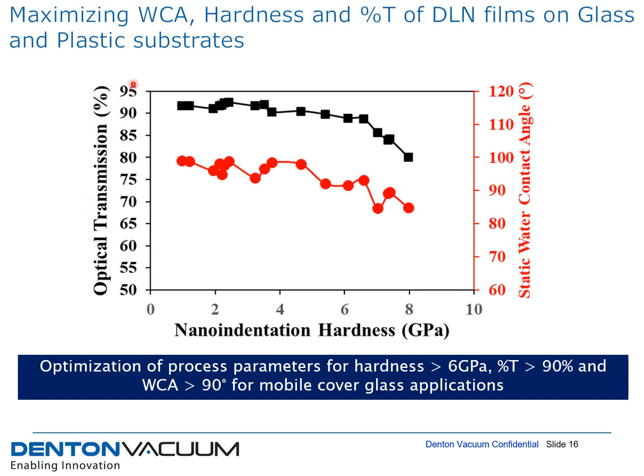What I have done here is plotted the optical transmission and the static water contact angle as a function of the nanoindentation hardness. You can see that for a hardness of around 6 GPa, you can get a water contact angle of around 90 degrees and an optical transmission of around 90%. But these are single layer films, and their properties can be further enhanced by a proprietary surface treatment process using the same ion source that we have demonstrated.